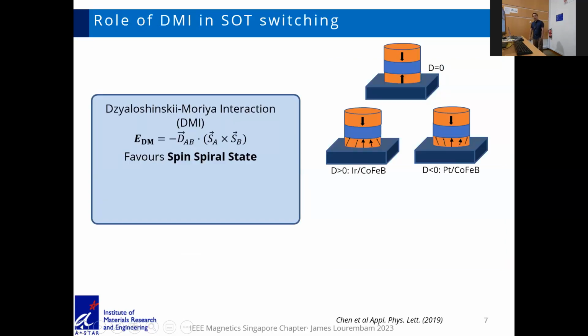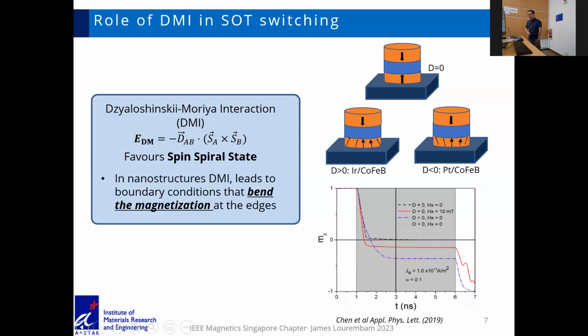Besides the spin Hall angle, the other material parameter that we started to look into is the Dzyaloshinskii-Moriya interaction. As I mentioned, there is an issue of switching a perpendicular magnet, because one would require symmetry breaking. So there are many proposals to get to symmetry breaking in perpendicular magnetic tunnel junctions. One of the ideas that we had was using the Dzyaloshinskii-Moriya interaction, which is an exchange interaction, and it favors a spin spiral state. So in a nano-size magnetic tunnel junction, the presence of DMI would tilt the magnetization at the edges. That would inherently break the symmetry and can lead to switching of magnetization, as shown in our work